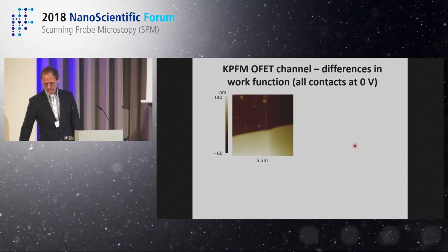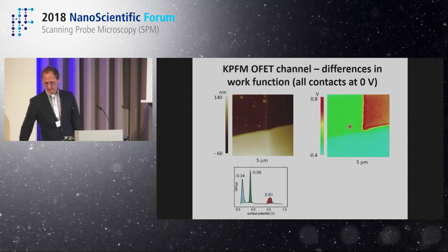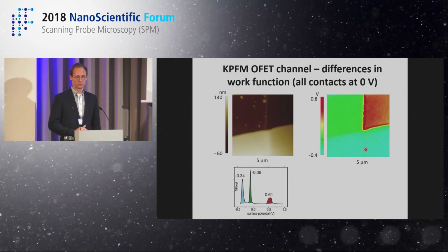Just the example from the transistor. This is the topography, the height. You can see even in the height that here you have the electrode, here you have your channel, and here you have your semiconducting crystal. So it goes from the electrode, it stretches into the channel. Now if you look at the KPFM, the surface voltage, you see that all three materials correspond to a different constant voltage, and that is because they're all characterized by different work functions.